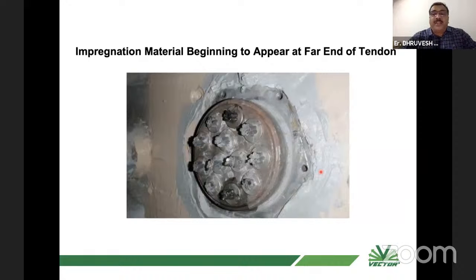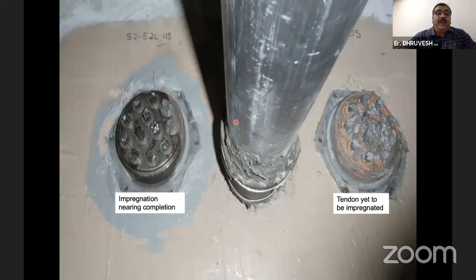Once we had started pumping, we went to the other side, and we saw that grout was coming from the lowest tendon and from the upper tendon. It had traveled up to 72 meters and was coming out. Then we waited further, and the photograph was taken at that time; it was almost coming from all the tendons except 2. We waited more, and then it was fully saturated. Then we pressurized it and kept it for purging for some time as per our design, and we see that all the tendons are being coated with this impregnation material. The right-hand side picture shows that it is not impregnated.